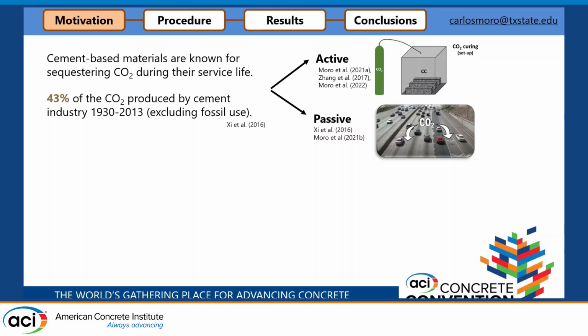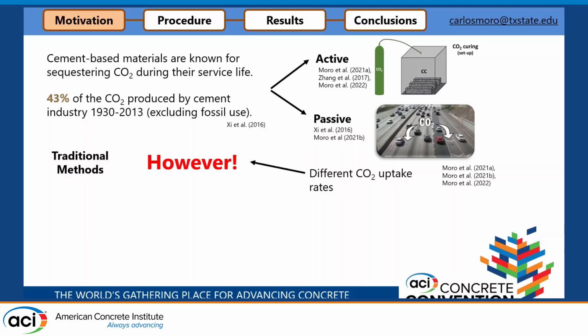And depending on the concrete that we have, the problem with this is that we will have different CO2 uptake rates. Different permeability will lead to different injection of CO2 inside the material. So in that case, we cannot quantify that. And the problem is that the traditional methods that we use, basically life cycle assessment, only have two ways. One is cradle to gate. So it's a picture at year 0. You produce the concrete, you estimate the CO2 emission, and that's it.